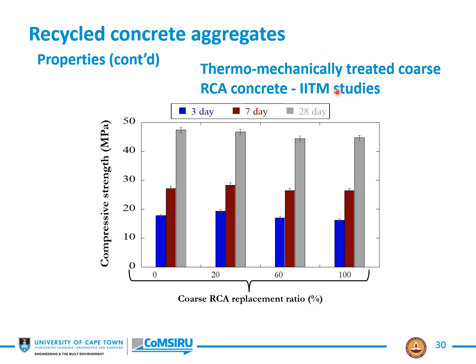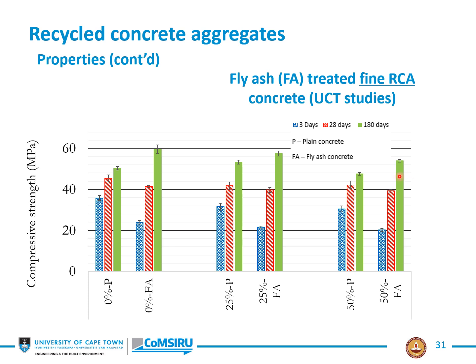This is where you virtually remove all the adhered mortar by thermomechanical treatment. And here you can see that for 3, 7, or 28-day strength results, there really is very little difference, and this aggregate is, to all intents and purposes, similar to the original aggregate itself. This is coarse aggregate, of course. Now, here's the approach that we've tended to take at UCT, where we've treated the fine recycled aggregates with, in this case, fly ash and slag. Here, fly ash.